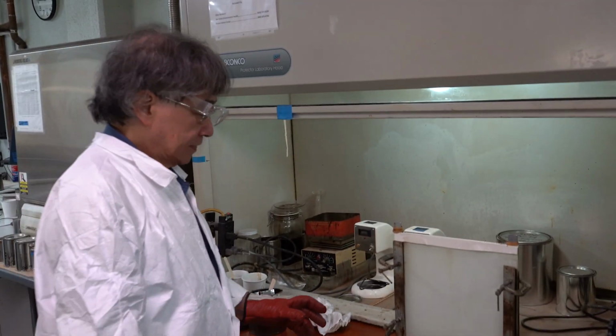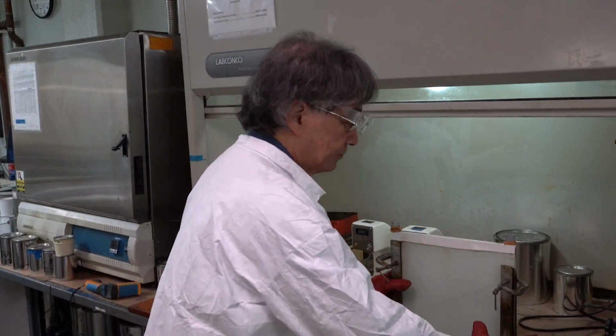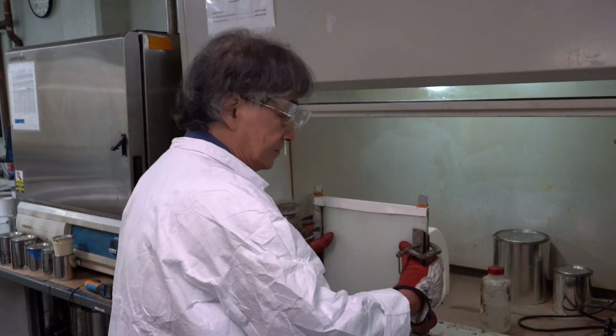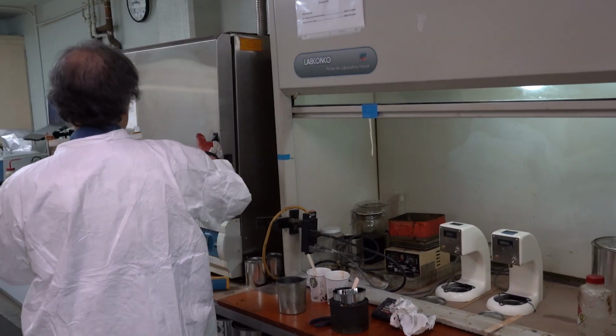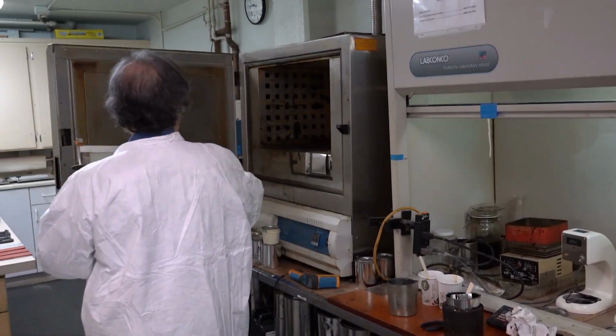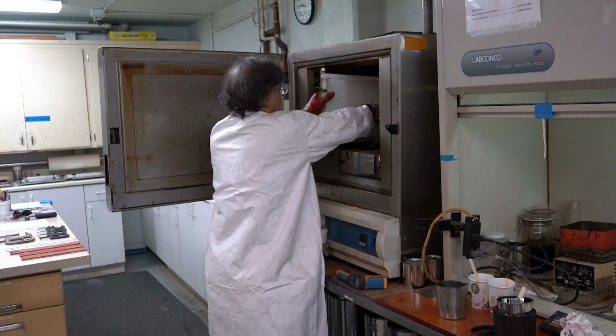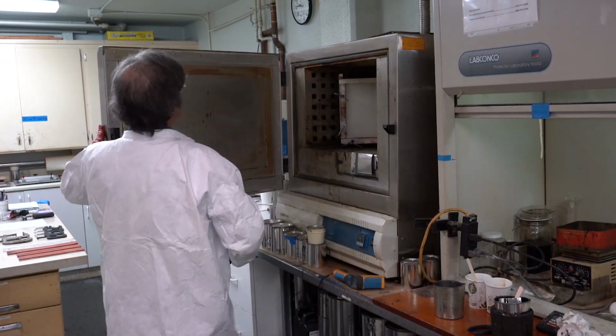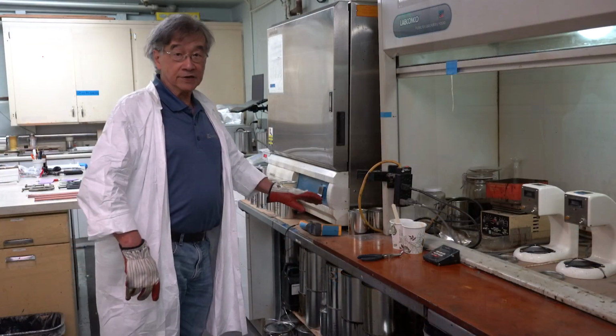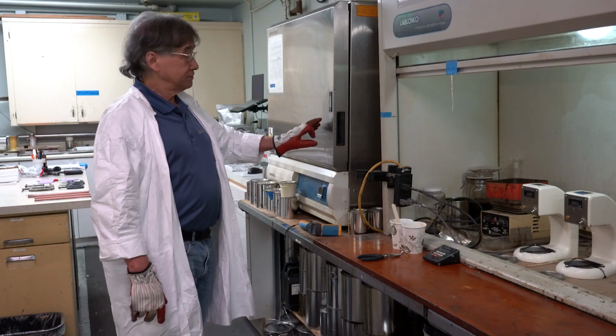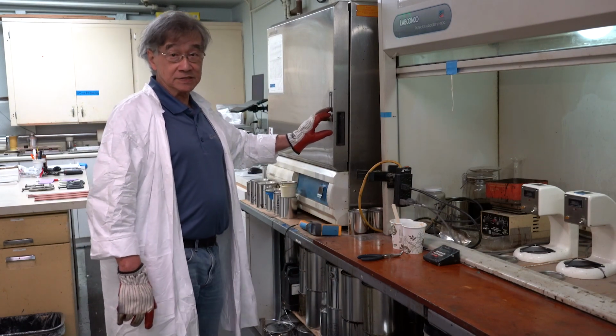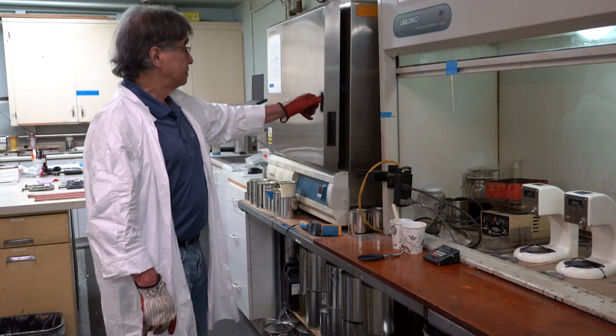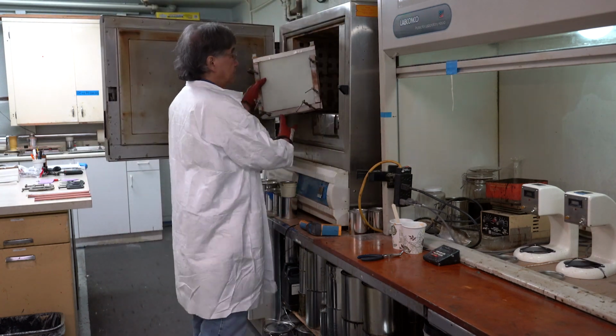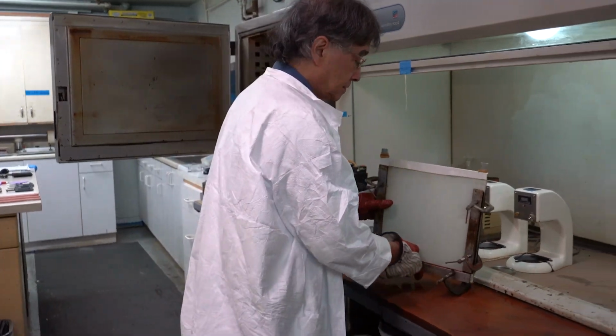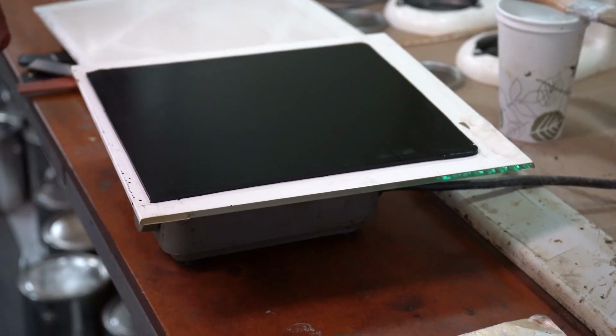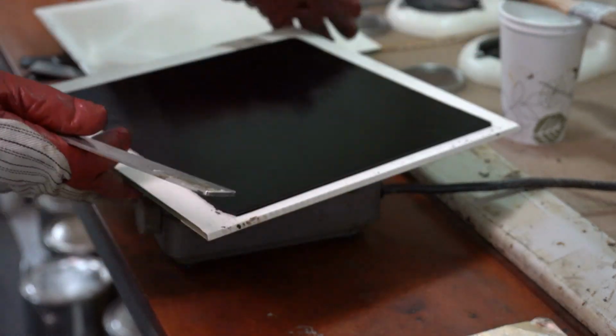Now the filled mold will be returned to the oven for the curing time, which is 4 hours. Now at the end of the 4-hour cure time, I'm going to dislodge the casting from the mold. This is a hard casting after the mold has been opened.